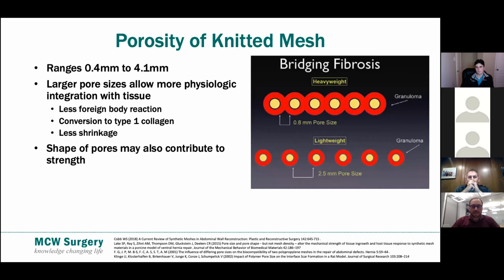The science behind the fact that the larger pore sizes allow more physiologic integration is a concept of bridging fibrosis. So if you have too close of a pore size, as we talked about in terms of that fibrotic reaction with the foreign material, the fibrosis bridges to the next polymer, and it creates basically an encapsulation around the mesh, which doesn't allow a proper tissue integration or cellular integration between the polymers. Counteract that with a larger pore size where you don't have the bridging, and it allows for cells to integrate in between that material. So that's a study that showed why the larger pore size is more desirable.